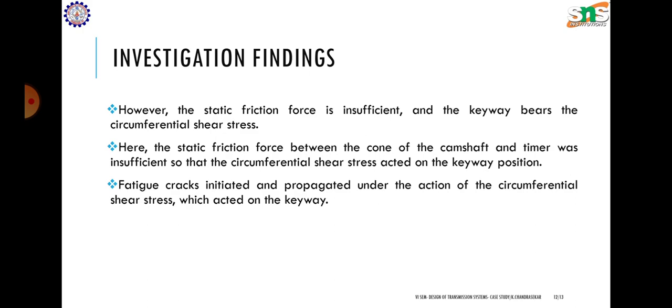It can be detected that in the operation of the injection pump, the static friction force between the cone of the camshaft and the timer was insufficient, so that the circumferential shear stress acted on the keyway position. Okay.